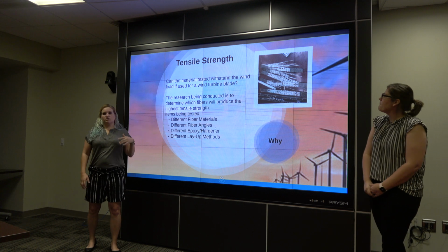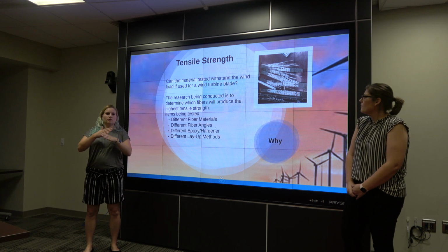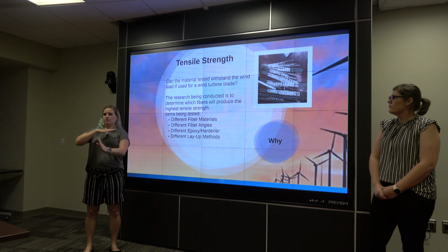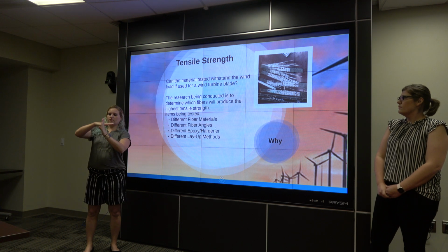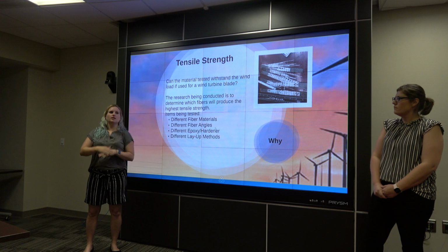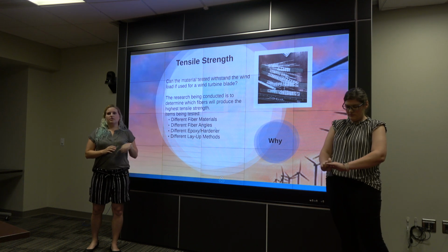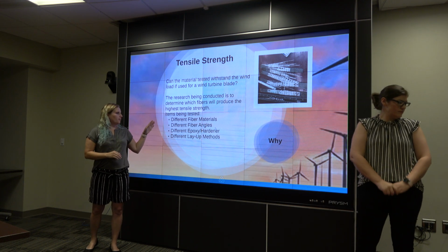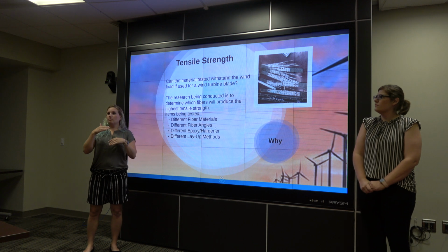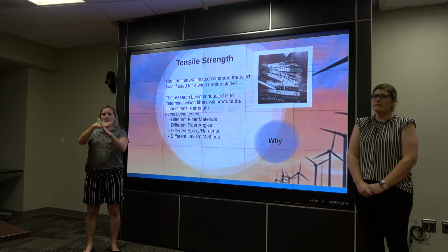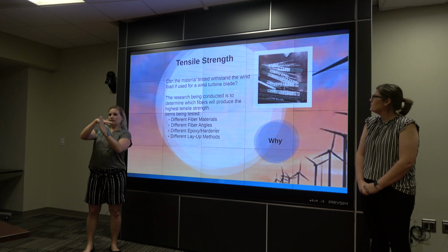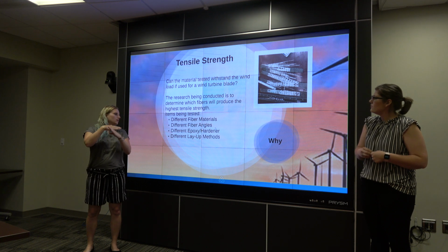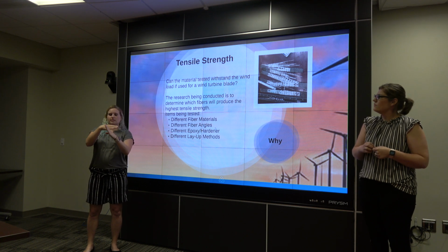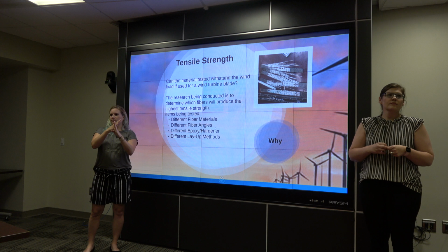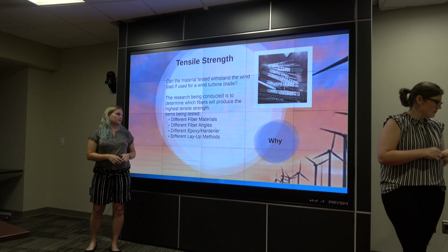We used actual different fiber angles. So if you don't know anything about carbon fiber, it is very intersectional, so just straight up and down constantly. But they also have a 3D printing machine where they're actually able to print using carbon fiber, and then instead of just doing it 90 degrees, they'll change the angles. So we looked at 12 degrees, 20 degrees, 45 degree angles to see if that would affect the strength.